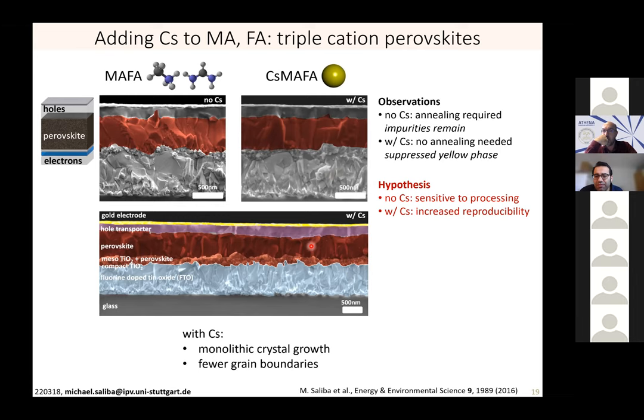So without cesium, there are many crystalline precursor states which are difficult to control. But the presence of cesium pushes it directly into the black phase, such that the formation can start from the correct phase to start with. And that's a very important issue because it explains some of the sensitivity of these materials. It's very difficult to process perovskites, even in a glove box atmosphere, because the atmosphere itself is exposed to the solvents that are required to crystallize this material. So it's challenging to get a repeatable result. But by adding the cesium, we could see that the correct phase was used from the get-go, and this was useful in terms of reproducibility down the line.